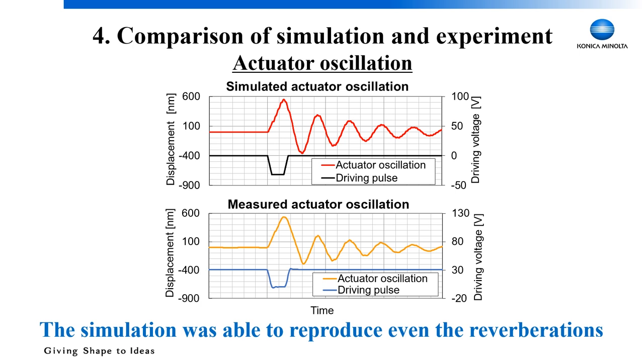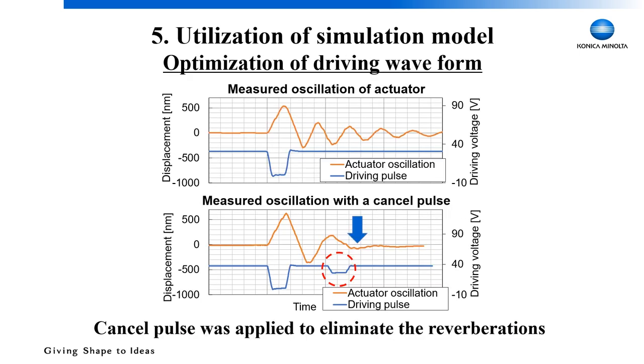Then we used this measurement to optimize the driving waveform. These reverberations interrupt the next jetting pulse when we use the printhead with high frequency. For example, if we use a frequency higher than 50 kHz, the next jetting pulse will come around this timing. Then we need to eliminate the reverberations. We applied a cancel pulse to eliminate the reverberation at this timing. We optimized the cancel pulse shape and timing to eliminate the reverberation by observing the actuator oscillation directly.